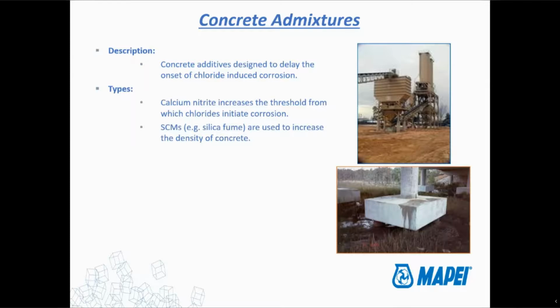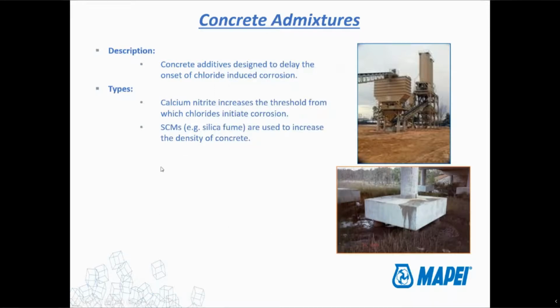The other one that gets used is what we call SCMs. These are supplementary cementitious materials. It's kind of a mouthful, so I'm just going to go with SCM. But this is silica fume, fly ash, those types of things that are just being used to basically increase the density of the concrete. By increasing the density of the concrete, you're just keeping chlorides out, you're keeping water out. Again, it's just trying to slow things down.